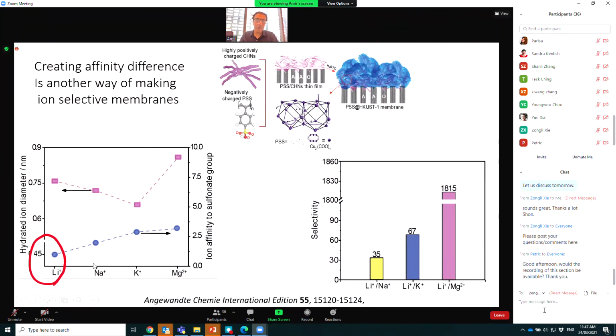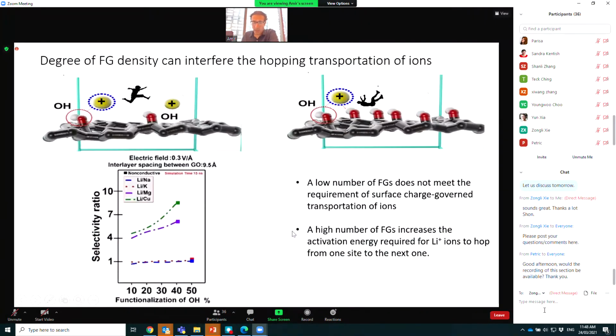For example, we know that lithium ions have low ionic affinity towards the sulfonate group. So basically, what it means is that the sulfonate groups can hold other ions and let lithium ions go through the nanochannel. So there are a few reports that use this different affinity of ions to create membranes to increase their lithium ion selectivity.